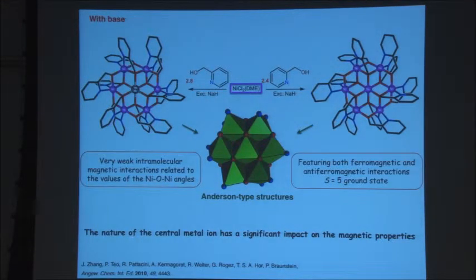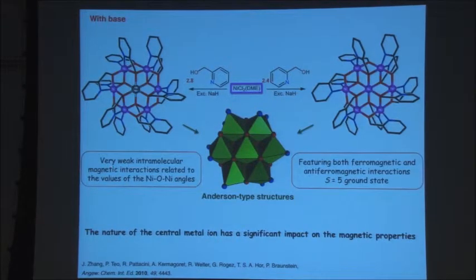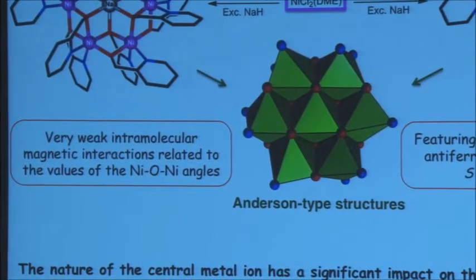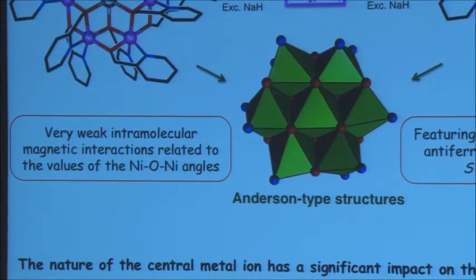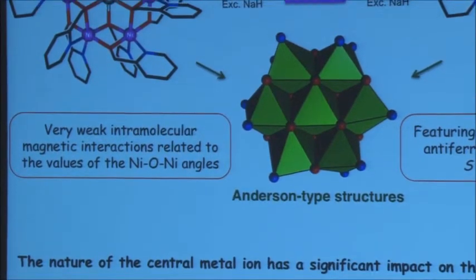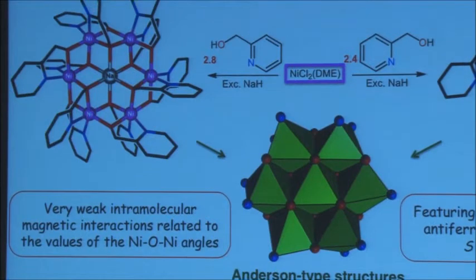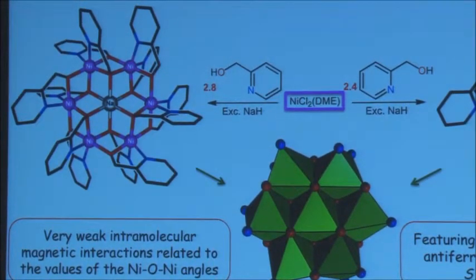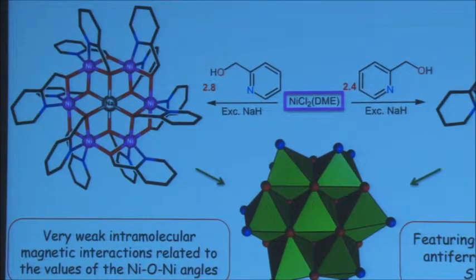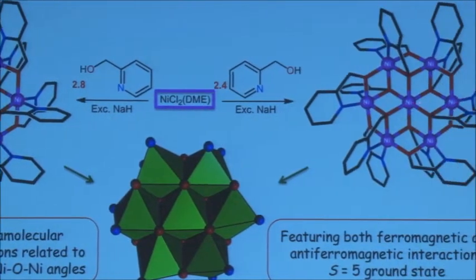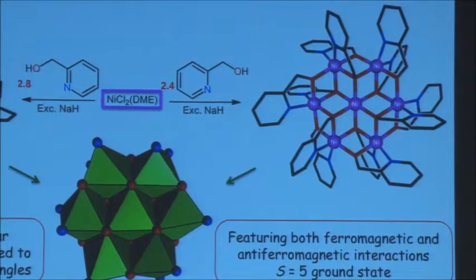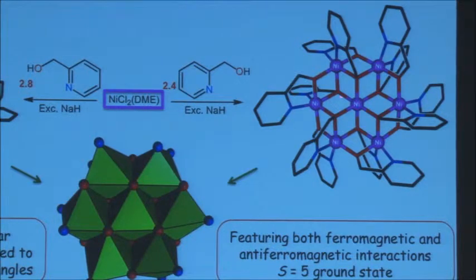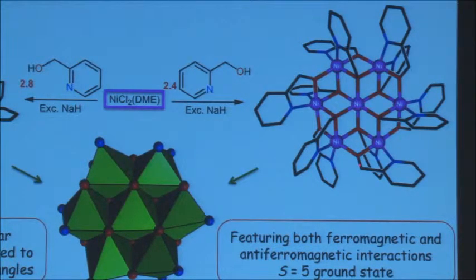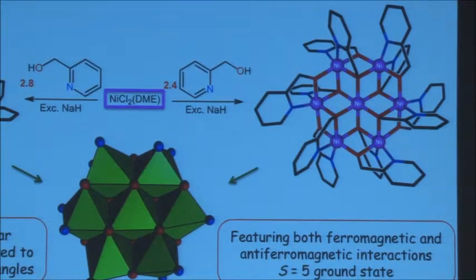So this one here has very weak intramolecular interactions. That's, of course, ideal to study the magnetism, because here you know that the center of the wheel is diamagnetic. Sodium plus has no magnetic properties, closed shell structure, that you can compare with the isostructural system with the nickel 2 center, which is paramagnetic here. So you can compare the interactions between the center and the periphery and between the nickel centers at the periphery. And this one has both ferromagnetic and antiferromagnetic interactions.